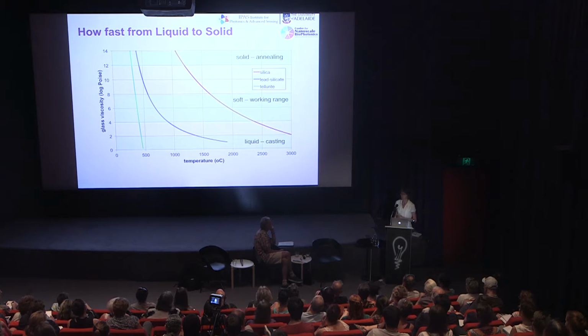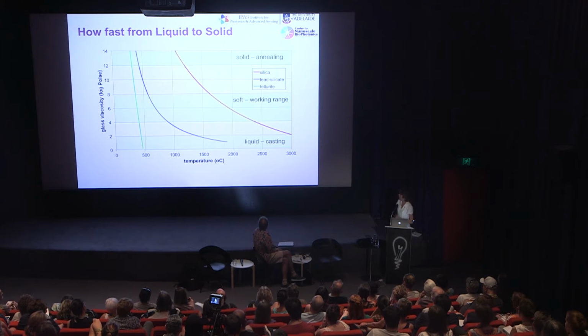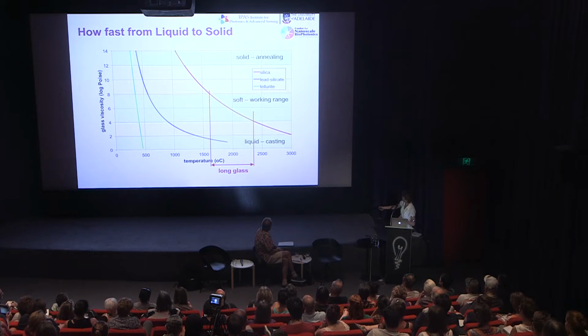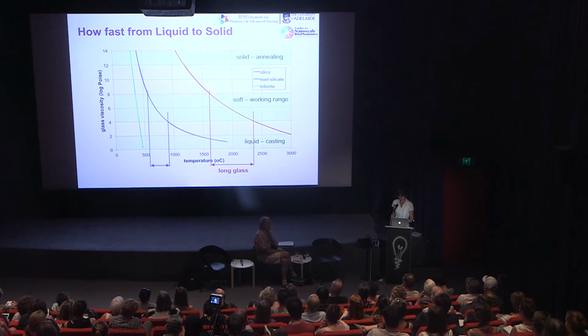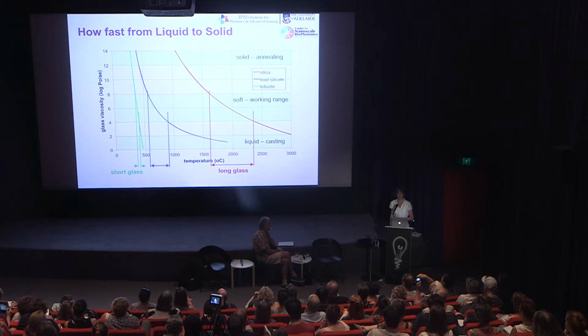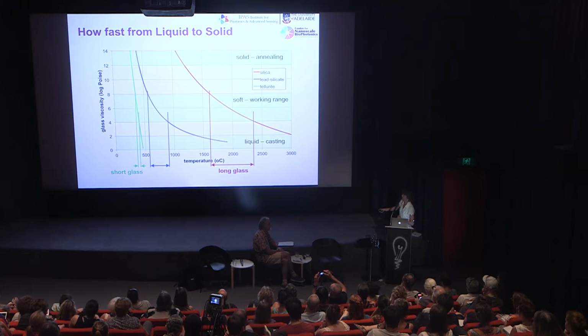And here I've shown the viscosity curves for 3 types of glasses: pure silica, lead silicate glass, and one of our special glasses, the tellurite glass. You see that these glasses differ in their slope. That means how the viscosity changes with temperature. If we see here the silica glass, you have a huge temperature range where you can work with the glass. To a degree, it's similar with lead silicate glasses, but the challenge with our glasses is really that you can see how small is the temperature range where we can do something with the glass. And therefore these glasses are called the short glasses. These are the long glasses because they have a long window in terms of time working with the glass.